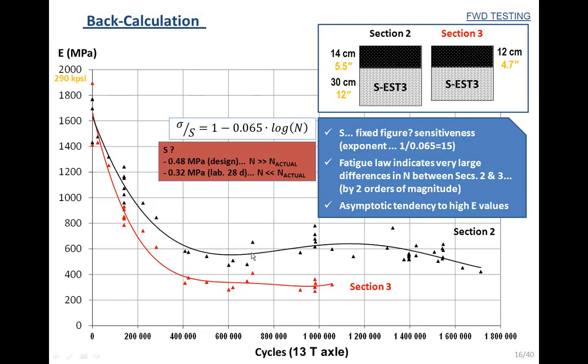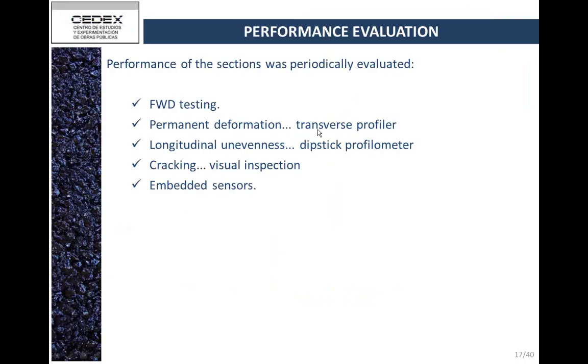We were really surprised to see that the modulus were stable in relatively high values, especially for section 2, because 600 megapascal, that's a very huge value, even though the material is damaged. So if this is the real performance of the material, then it could be really great, because even after damage, the material would be able to retain a very high modulus. So this was the other question: why are we getting this stabilization for such a large value of the modulus?